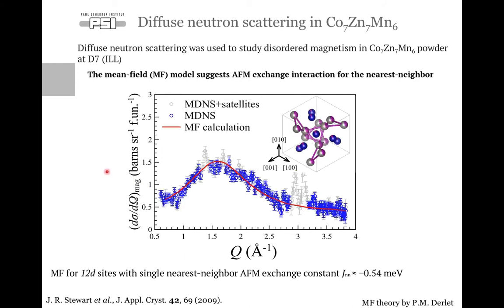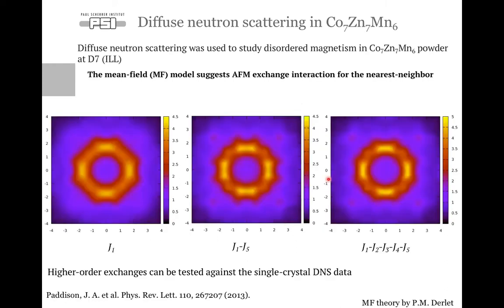And the mean field model proposed by Peter Derlet from PSI suggests that these short-range antiferromagnetic correlations are due to the nearest neighbor interaction between neighboring manganese ions situated at the 12d sites. And this model corresponds well to the experimentally observed diffuse neutron scattering pattern. So we don't need to go beyond the first neighbor interaction to reproduce the data we have at hand.